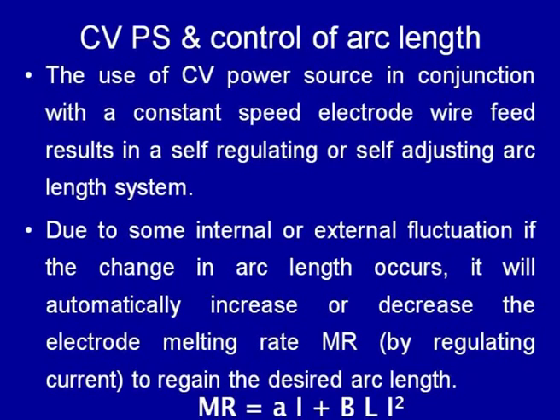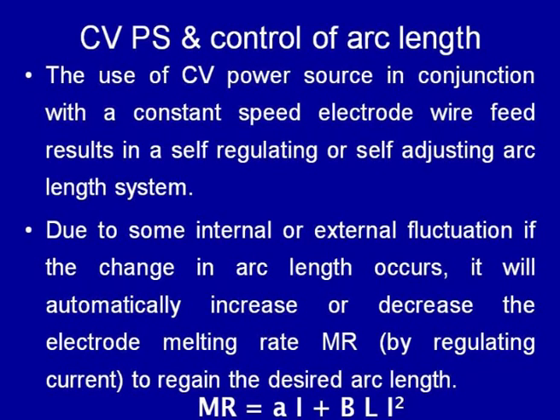So, how is this achieved, to maintain the constancy in arc length while using the constant voltage power source in conjunction with the constant speed electrode wire feed system? This kind of combination results in the self-regulating arc, and the self-regulating arc automatically produces the adjustment in arc length so that it remains constant. So, a combination of the constant voltage power source coupled with the constant speed electrode wire feed system produces the self-regulating arc system, especially when the electrode resistivity is high and the diameter of the electrode wire is small.